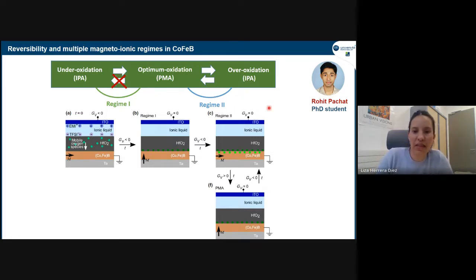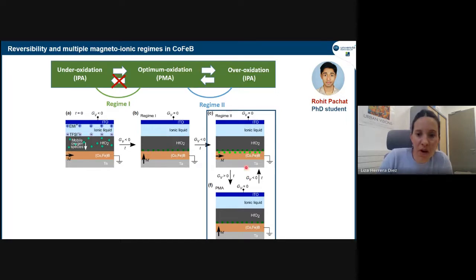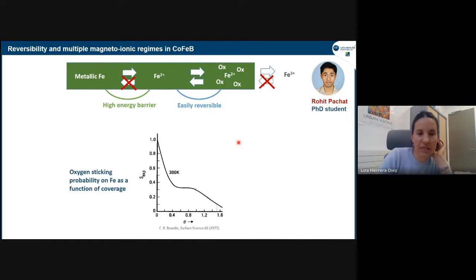And what is interesting is that this is the part that can go back and forth, the part where we have oxygen that might be less bound to the layer. So why am I saying this? Because we start from metallic. I mean, we're going to simplify the system a little bit because we have cobalt-iron, but this is an iron-rich film. So we could simplify it to the point of saying that we just have iron. We could do the same with cobalt. But here we start, let's say, with metallic iron before we do anything.